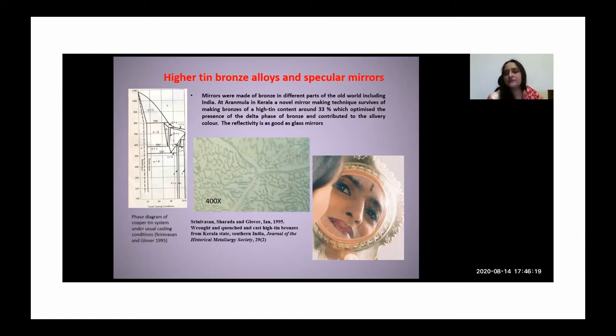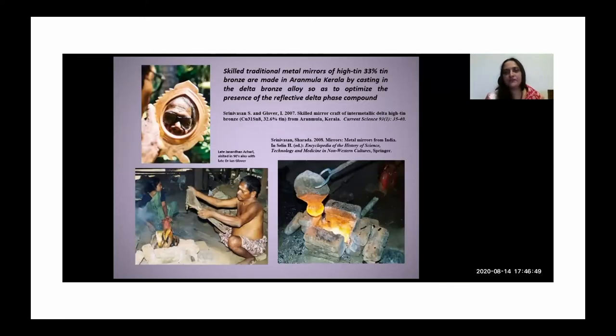And in these metal mirrors, of course, there's no refraction, so it's really a point image. So in fact, it's completely reflective across the spectrum. So it's really a very brilliant kind of mirror finish. But it's interesting, I should tell you that in the photograph which was taken of me looking at the mirror some years ago, the whitish things that you're seeing, I also took that deliberately at that angle, because those are actually the large crystals of the delta phase, because the delta phase forms these large crystals. So you can almost see the shape of some of those crystals as well.